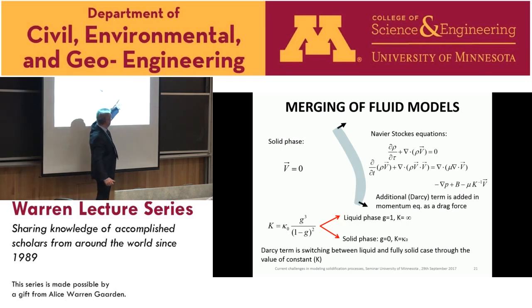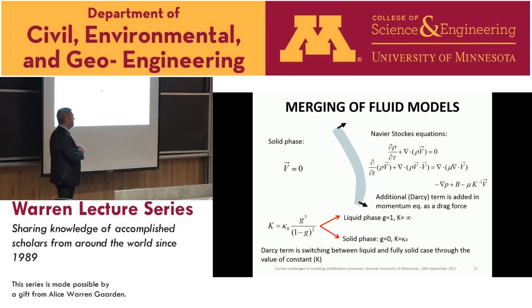Above the infinity is a 0, and this term is disappearing for the liquid phase. You can find this equation in the book on porous media. In the solid phase, G is equal to 0. That means K is equal to K0. And because this constant is very small, 10 to the minus 10 or 10 to the minus 11, there is a theory on how you can calculate it.